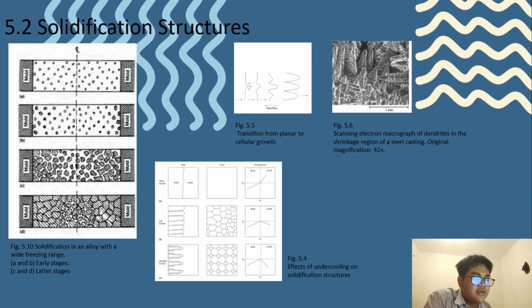In pure metals, undercooling can result from thermal supercooling, while in alloys it can result from a combination of thermal and constitutional supercooling. And in figure 5.5, we can see the transition from planar to cellular growth. It occurs when the advancing planar solid-liquid interface becomes unstable and a small spike appears on the interface that then grows into a cellular type structure.